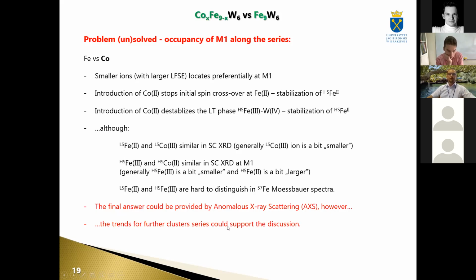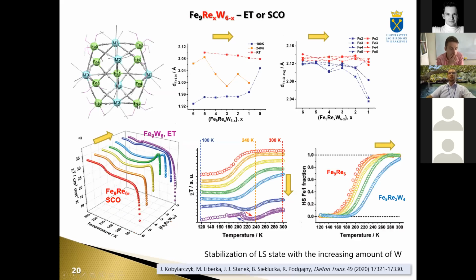Now let me focus your attention on another series. Here we performed similar studies for iron tungsten rhenium mixtures. So now we played not with metal ions in this position, but in this position. And here are the magnetic data, Chi-T product over T. And from this comparison, we clearly see that in most of the phases, we observe the spin crossover, but with low temperature phase stabilization, depending on the amount of iron and depending on the rhenium and tungsten.